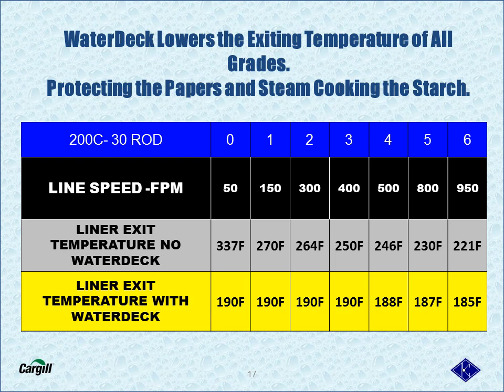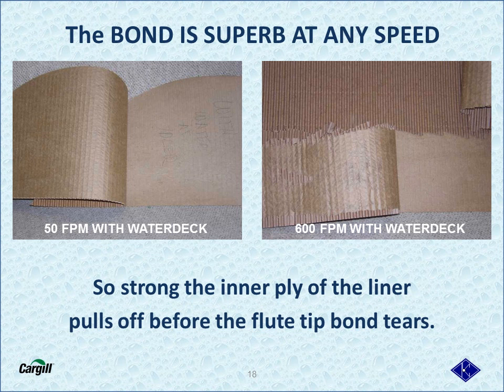On an isothermal corrugator, you can lower the exit temperature even further, but look how flat the speed curve is versus temperature. As the speed goes from 50 to 950 feet per minute, there is only a 5-degree change in temperature on the bottom liner. Thus the name, isothermal corrugating, where you can now maintain a constant temperature over the entire speed range. The bond is superb at any speed. Over a wide speed range, we maintained exceptional bonding so strong, in fact, that we pull the inner ply of the liner off with the medium, instead of getting failure between the medium and the liner.